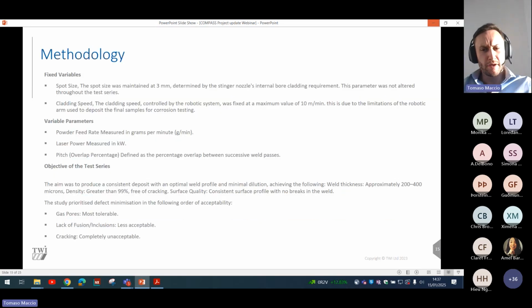So following that, we had a methodology of what we wanted to do for the trials. So we wanted to have a fixed spot size of 3 millimeters, because this is predetermined by the internal bore. Clad speed we wanted to keep at around 10 meters per minute for the samples that will be tested. This is because the samples that are tested are not on a shaft, they're on either a plate or discs. So this needs to be done on the robotic arm. The robotic arms can't move at much greater speed than 10 meters a minute with extreme accuracy. So we had to do a fixed speed of around 10 meters a minute.